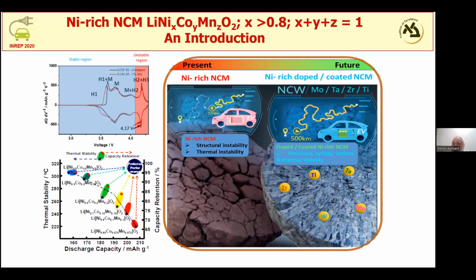We have the family which is called nickel-rich NCM. And you see here the formula. The lithium stoichiometry is 1, nickel, cobalt, manganese together, again, is 1, and oxygen is 2. And with this stoichiometry, we charge the cathode up to 4.3 volts versus lithium.